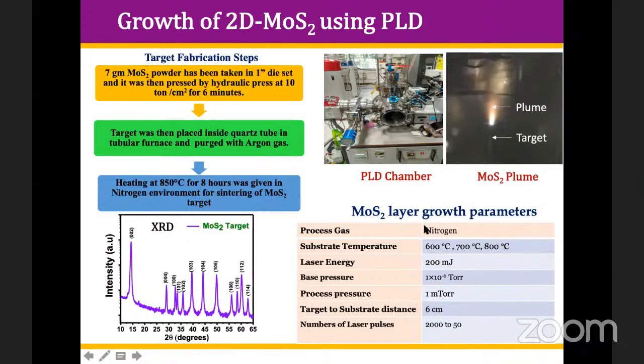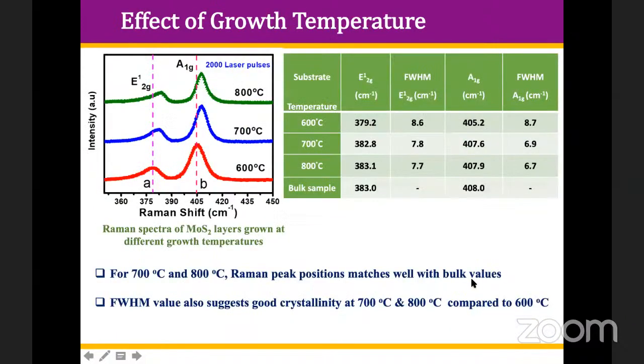Parameters have been changed. Mainly the substrate temperature has been changed so that we can grow a good quality MoS2 layer. Just see the example here. We have changed the temperature, and this is a Raman spectroscopy of the thin film which has been deposited. Two modes, E12G and A1G, which are well-defined modes of MoS2 in the literature, have been obtained. And you can see the literature.